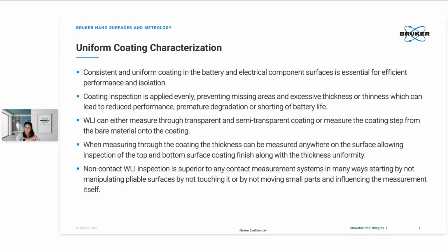So with the technology of WLI, you can either measure through transparent or semi-transparent coatings, or you can measure the coating step from the bare material onto the coating. And when measuring through the coating, the thickness can be measured anywhere on the surface, allowing inspection of the top and bottom surface coating along the whole thickness uniformity.